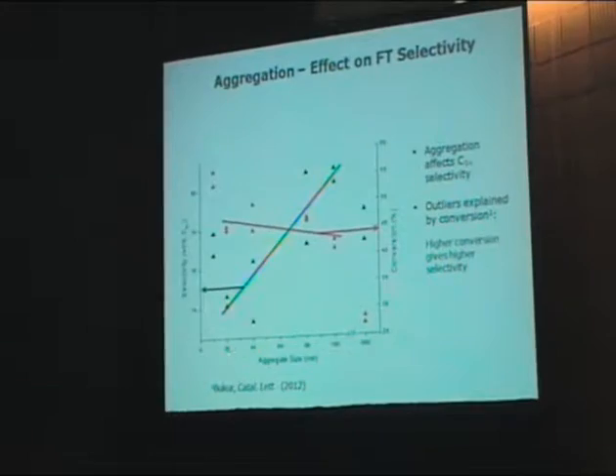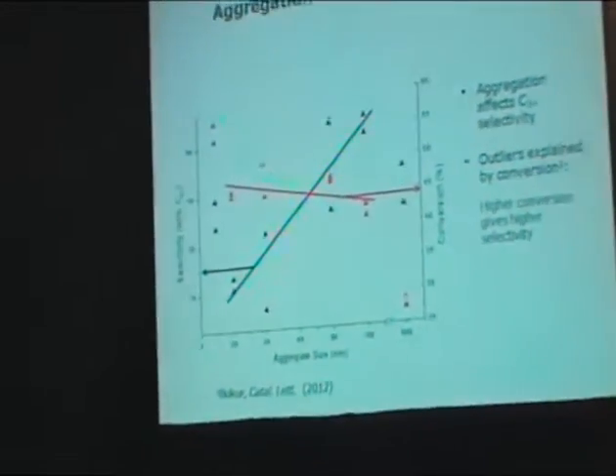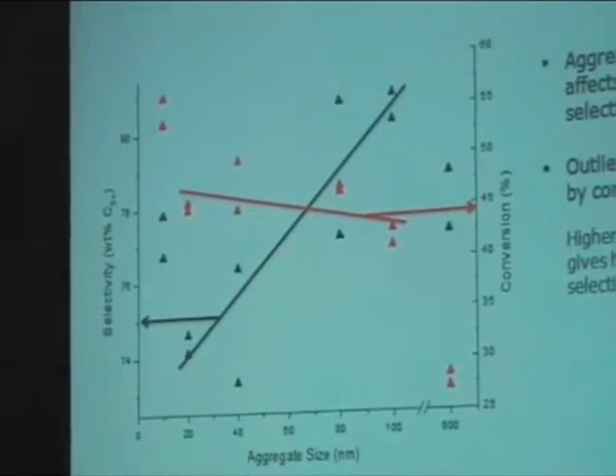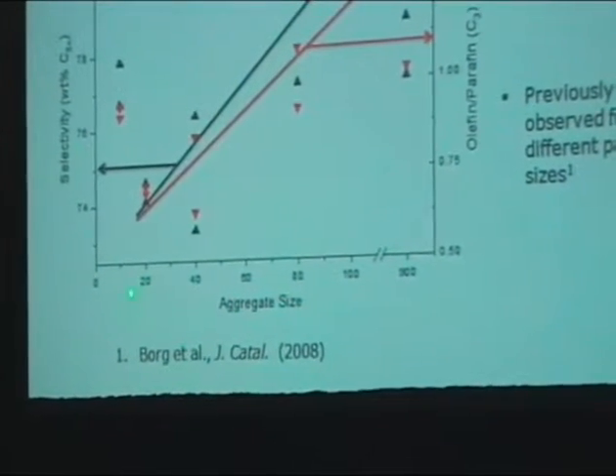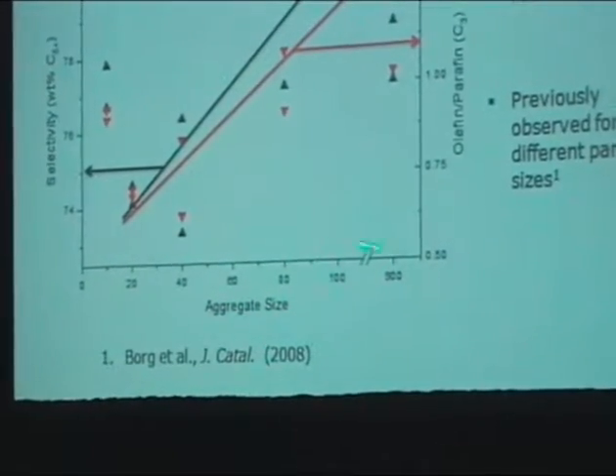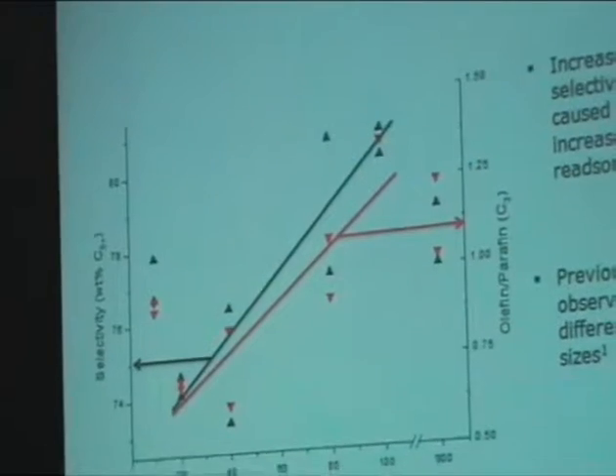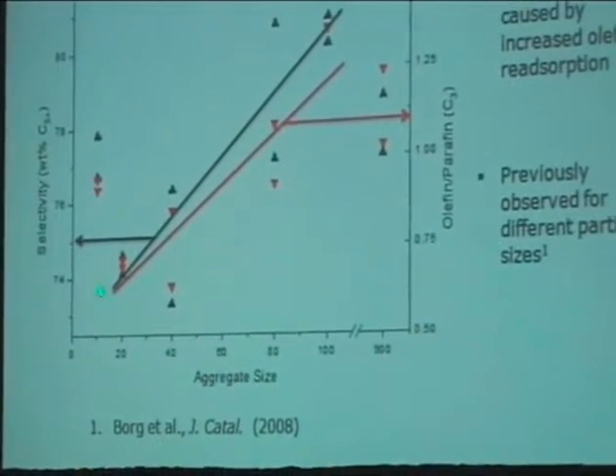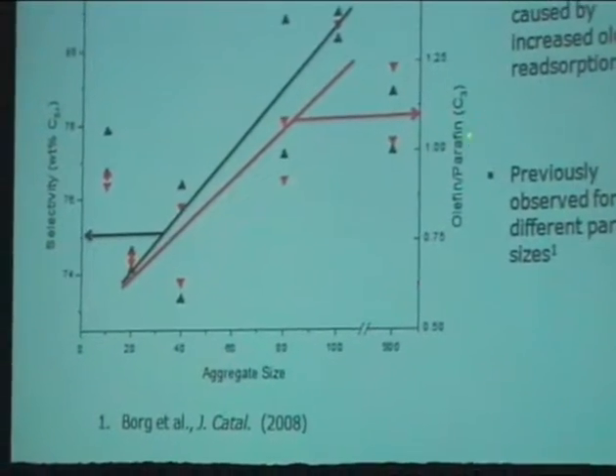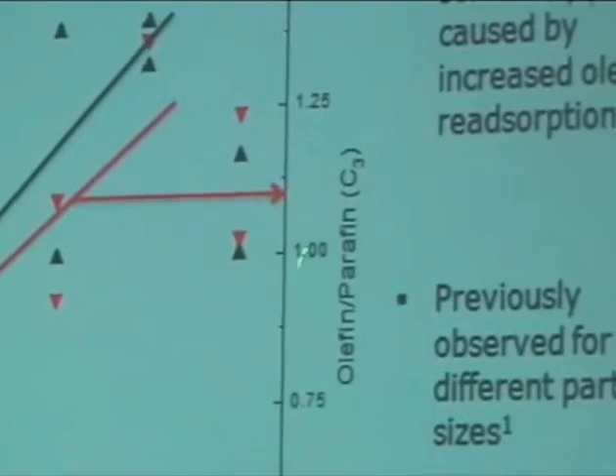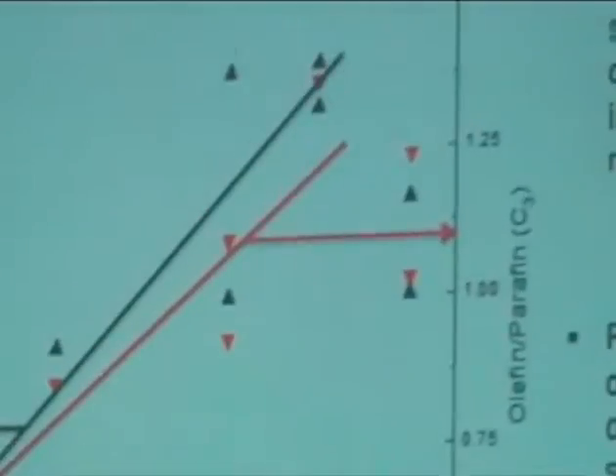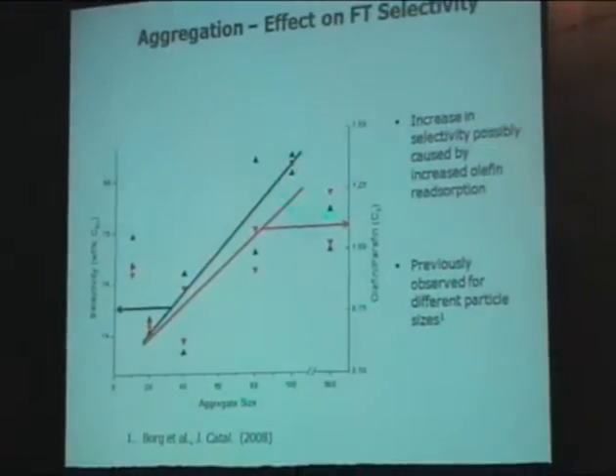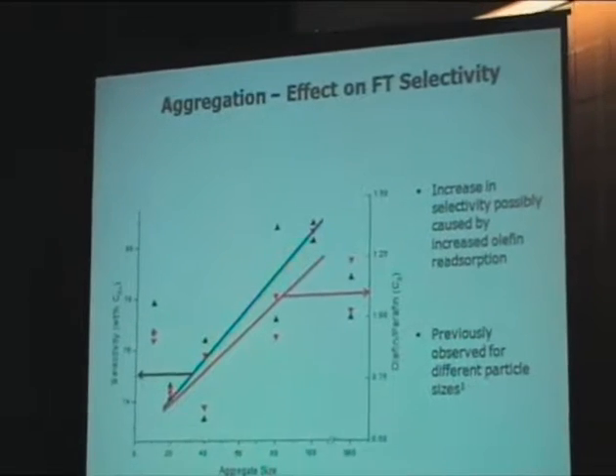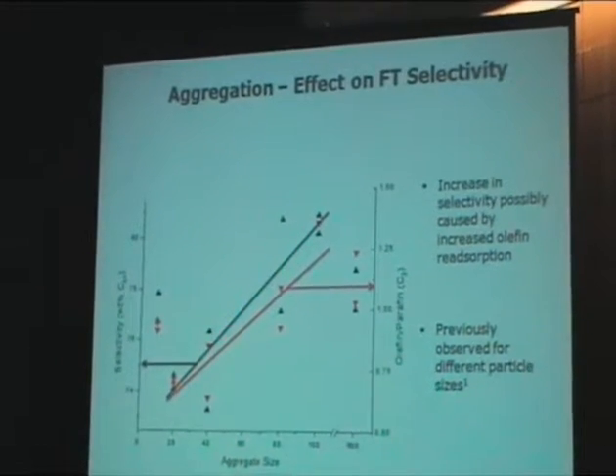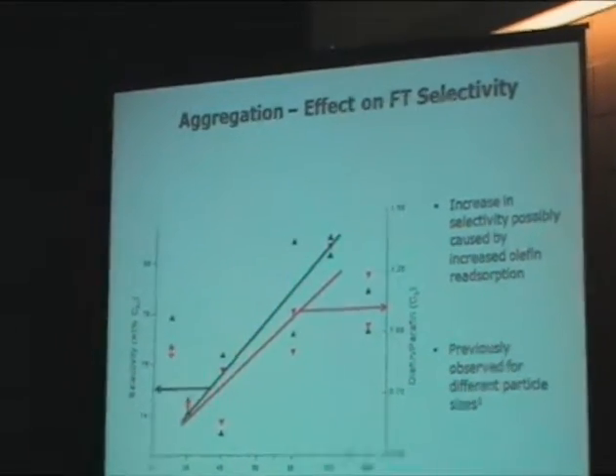So we have to work this out further, but it reminds us, on the one hand, of this conversion effect, which of course is known. For example, very recently, Bukur has published about that. But another one that's very important, and the Borg group has published that a few years ago, is that if these aggregate sizes, or as they refer to them, the primary particle sizes, were larger, the C5 plus selectivity went up. And what we noted is that the olefin to paraffin ratio, plotted on the right-hand axis, increases with aggregate size. It seems that we have a more olefinic product in the case of larger aggregates, and of course that may give rise to secondary reactions and higher C5 plus selectivity. Clearly more work is needed, but I think the observations are very intriguing.